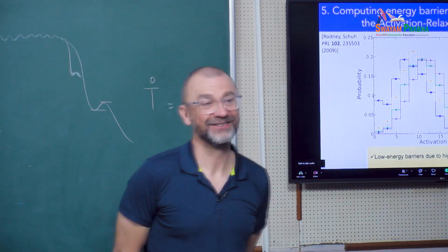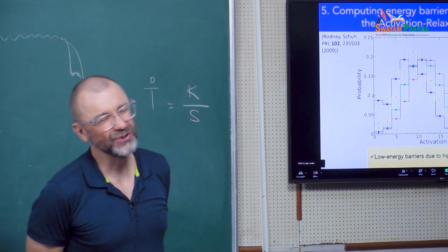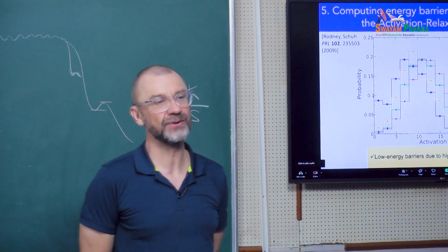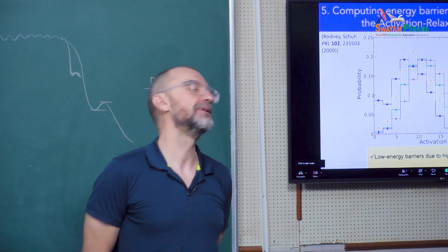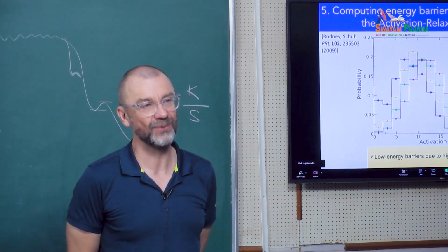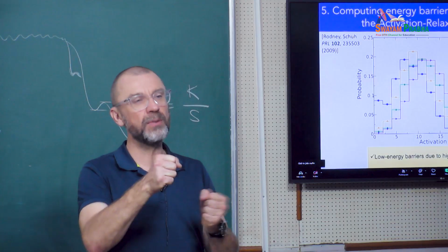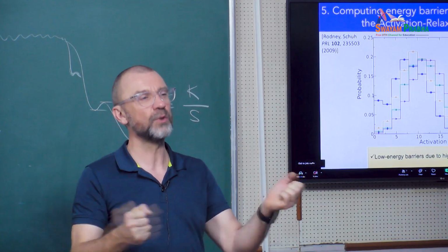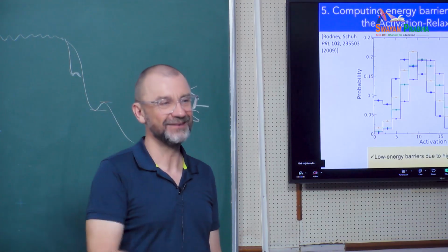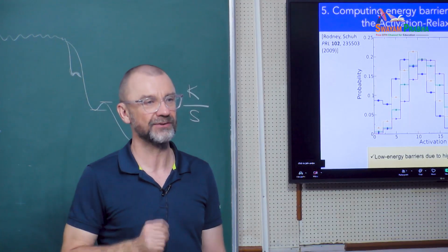Yes, it's difficult to know. Usually what people say is that in a metallic glass where there are no strong bonds, the number of saddles increases exponentially with the number of atoms. In systems where you have strong bonds like silica, the network glasses, then it's closer to linear, but it is still so big that we'll never be able to get all the saddles.